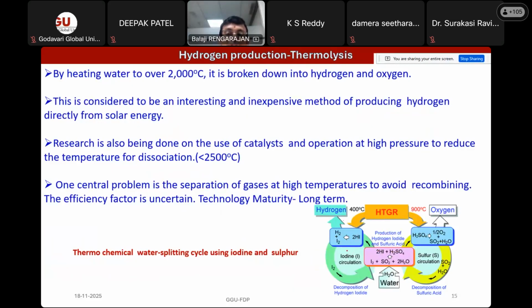Here, this technology is also not matured because of recombination. Though 2000 degrees Celsius is required to do the thermolysis, when you introduce this hydrogen iodide and sulfuric acid, the sulfur-iodine cycle, you can slightly reduce the operating temperature to close to 900 to 400 degrees Celsius. But even in that case, there is a possibility of recombination of hydrogen and oxygen. Because of these challenges, this technology is also not at a mature level like photolysis.